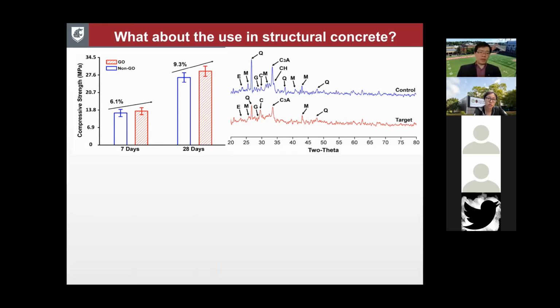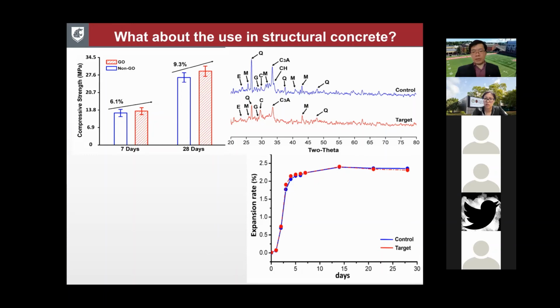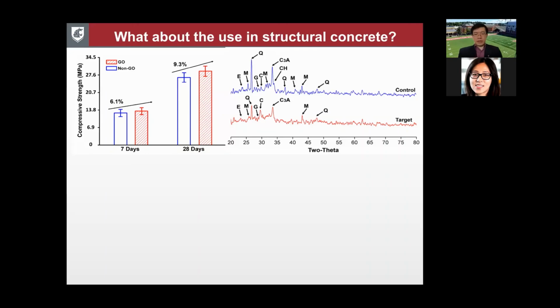In this case, we further explore this technology and try to remove the calcium chloride and use some other activators. We're achieving slightly less compressive strength, but we adjust the rheological behavior and setting behavior. And here the control is the one without graphene oxide. The target one is with the trace amount of graphene oxide. And we basically developed this as a rapid setting expansive cement. All right. So again, this one is corrosion free, and so we can potentially use it for structural concrete.